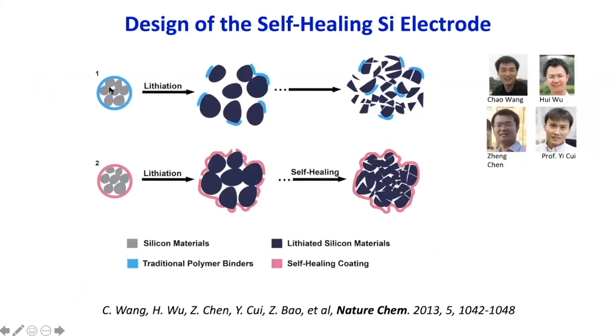for silicon, on top the particles are representing silicon particles for the anode. And then if you lithiate, one silicon can hold 4.4 lithium, and then this lithium will take up volume. So the silicon particle will have a big volume expansion as high as 4 times its original size. And when we make these electrode materials, we can't just put powder, because the powder will just fall apart when we try to make an electrode. So we need to have some polymer. So that's represented by the blue part, the blue coating. And this blue part is the polymer that's supposed to hold the silicon particles together.